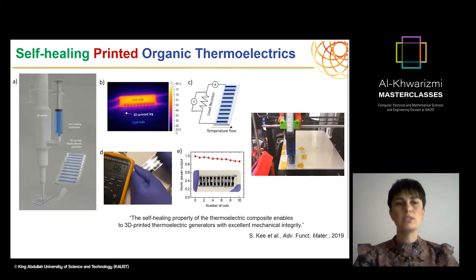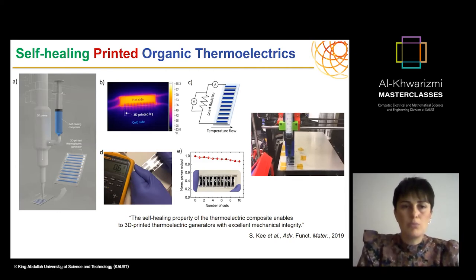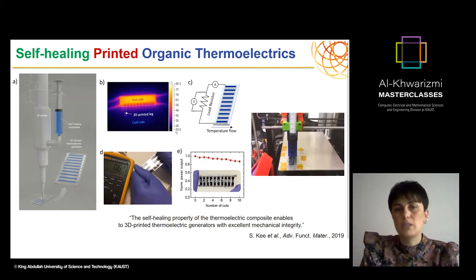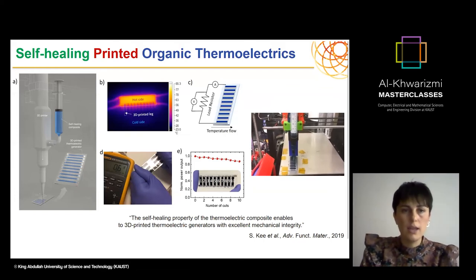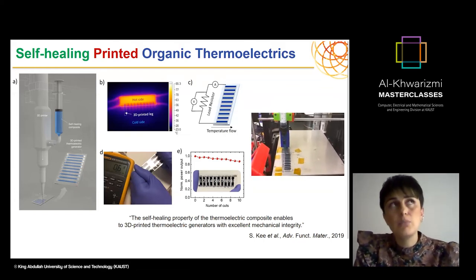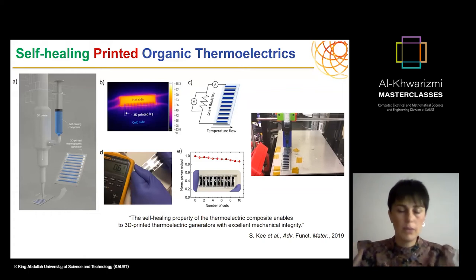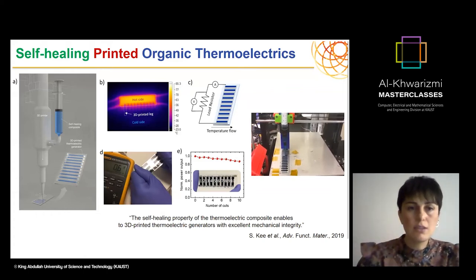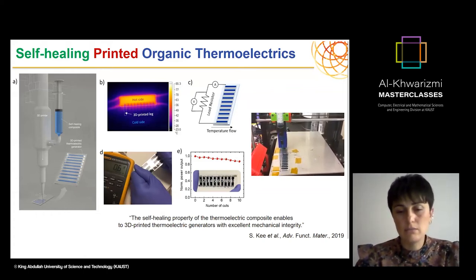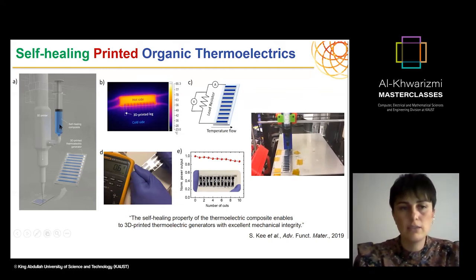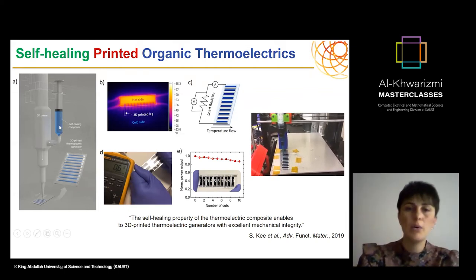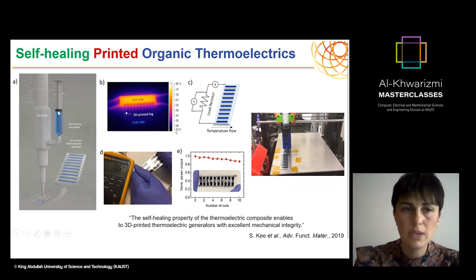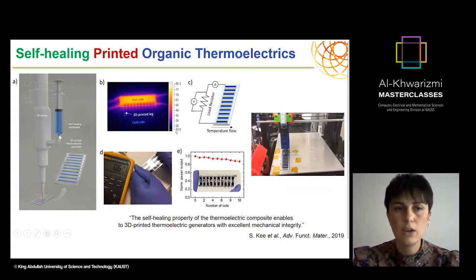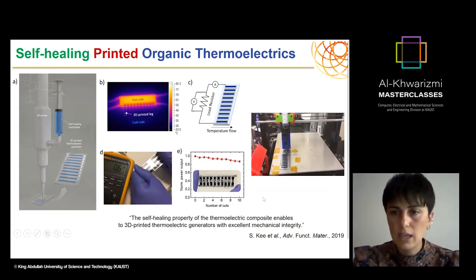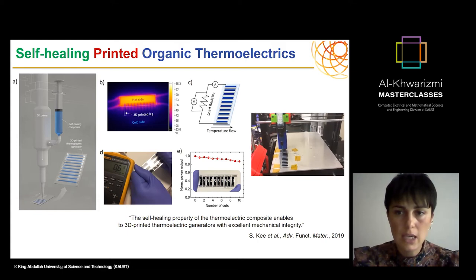And that was when we started to think about 3D printing and if it could be viable for such materials, which was not done before. And obviously for this reason, 3D printers, as you know, the commonly commercially available ones are actually using filaments and viscous inks, or solid filaments. However, in this case, we have non-viscous inks and we had to modify the 3D printer that could accommodate this property.